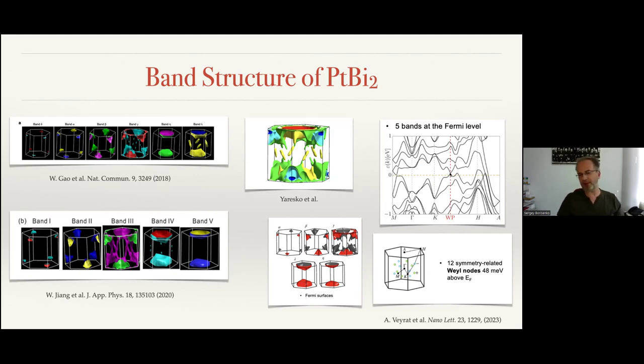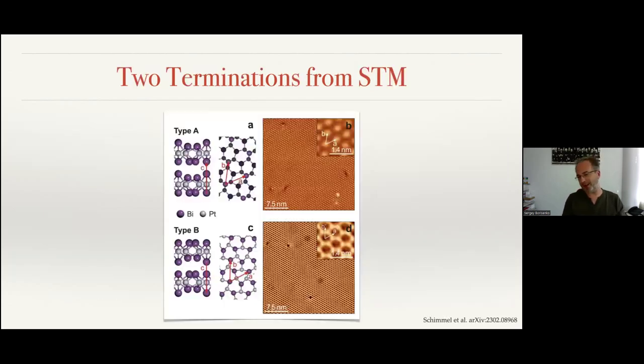Of course, if the band structure is of the type of a Weyl semi-metal, one expects interesting properties also at the surface. These are the results of my colleagues who did scanning tunneling spectroscopy. Here you see that the material cleaves and gives a very nice surface. This is very important also for our measurements. What they saw is that there is a type A and a type B surface, which is not surprising because the material is non-centrosymmetric.